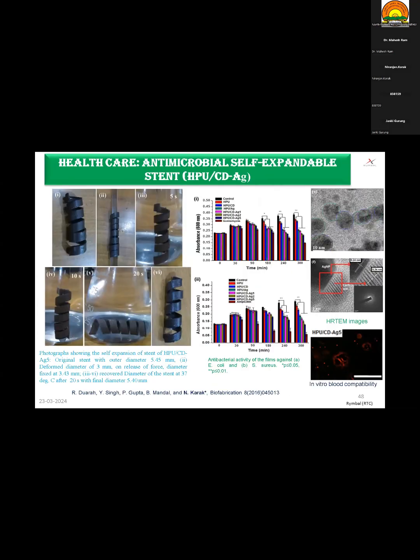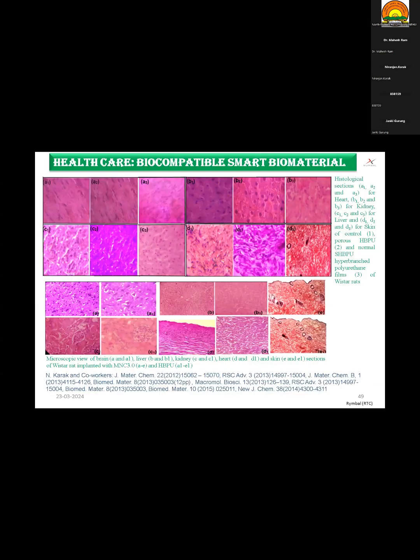Then there is the self-expandable stent. When there is a blockage in the heart, artery, or biliary system, you have to use a stent. Metal stents are very painful, whereas polymeric stents, used within a couple of years, form biofilm, and hence there is a need for replacement. In our research, we have shown that you can make an antimicrobial stent which will self-expand almost 99% at body temperature, and with its antimicrobial efficacy it will not allow biofilm formation, so you can use it for a longer time. All these materials are biocompatible, as we tested by pathological study, where there is no change in the major organs of a Wistar rat after implantation of this biomaterial.